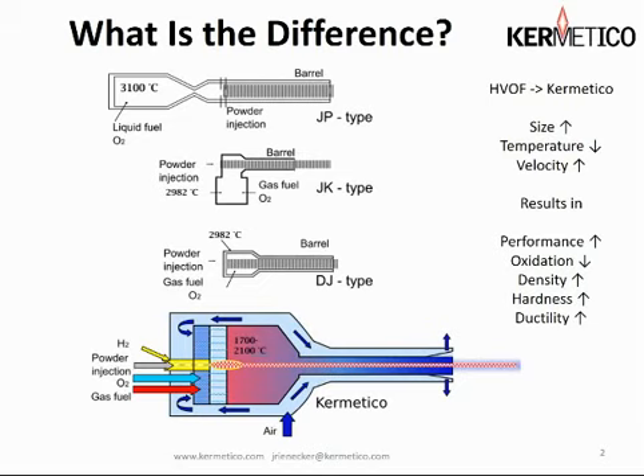The result of all of this is that we have very high spray rates, 60 pounds an hour for carbides plus 50 pounds an hour for metals. Oxidation is negligible because we're using it mostly in combustion, and we have the hydrogen to scavenge any leftover oxygen.